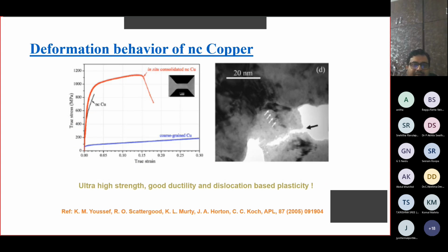So, again, as I said before, in addition to strength, reasonable levels of ductility is also important. I just now mentioned that around 10 nanometers, the existence of dislocations is a major problem in these materials. But again, you also cannot make larger samples which can be tested using our ASTM gauge standards and so on. See, anytime somebody says that I'm measuring mechanical properties, the first and foremost thing that we do is the tensile test. For that, we need samples of about 20 or more than 20 centimeters in dimensions. But you cannot make these nanometals into those dimensions. So therefore, you always make some kind of sub-size samples at micron scale or at millimeter scale, and then test them and find out some kind of relation between these properties and the conventionally measured properties.